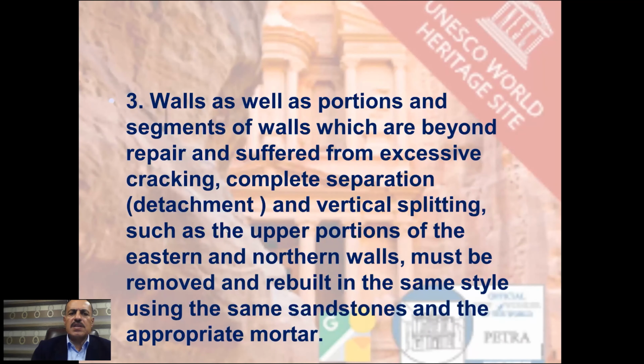In case of complete separation and detachment and vertical splitting, such as the upper portions of the eastern and northern walls, this must be removed and rebuilt in the same style. Some people might think this is really drastic, and in terms of conservation, people tend to be conservative. But in order to preserve and safeguard this structure, the whole monument, sometimes you have to compromise.